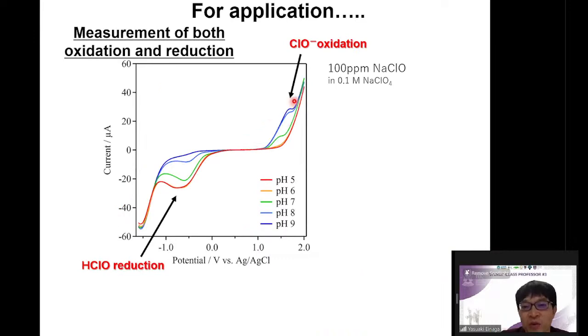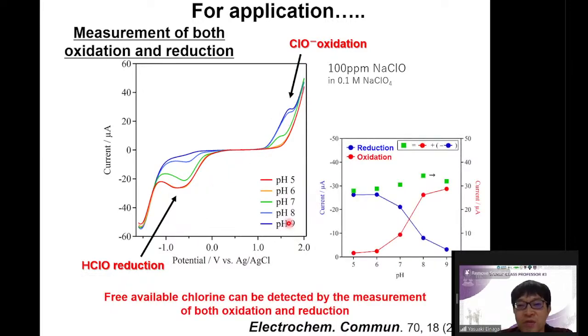Okay, so this is the result of both oxidation and reduction. As you can see, for application, the measurement of both oxidation and reduction is important. In the case of oxidation, this shows the ClO minus oxidation, and this reduction shows the HClO reduction. So then it shows the pH dependence like this. This is reasonable. So we confirmed the total should be the total of these currents.